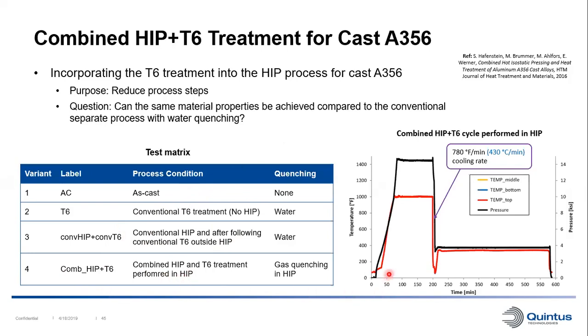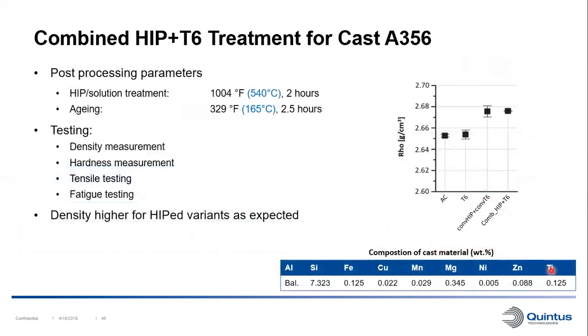And we can see the log data here from that HIP cycle where we have our combined HIP and solutionizing step, then we quench down to room temperature, and we also do the aging in the HIP. And here we can see some info of the process parameters. The testing that was done was density measurements, hardness measurement, tensile testing, and fatigue testing. And we can see the results in terms of density here on this diagram.